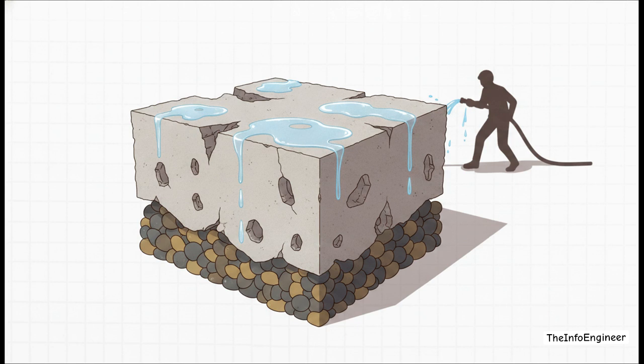Bumping that ratio even slightly can literally slash your 28-day compressive strength by 15 to 20%. Not to mention, it causes your heavy aggregates to sink, which we call segregation and bleeding, and leaves your concrete highly permeable and completely vulnerable to future water damage.